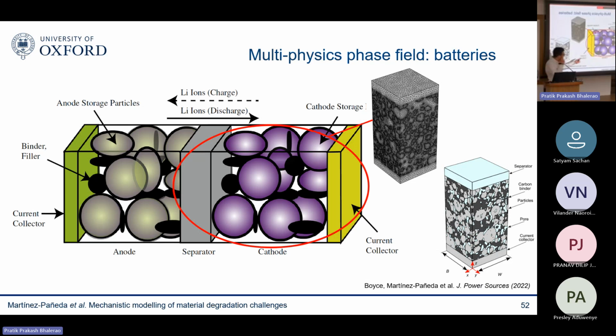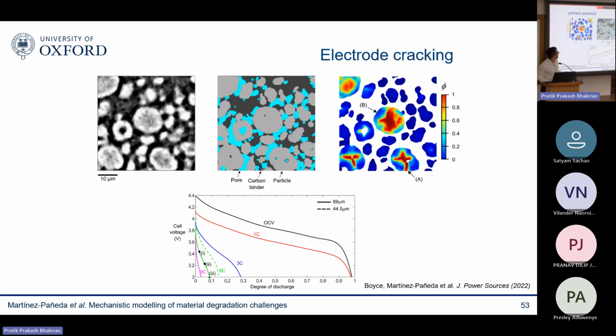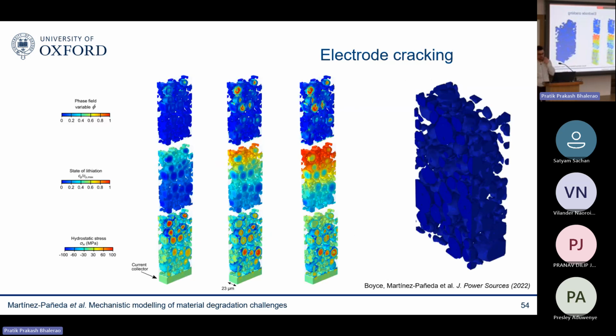But we also look beyond a single electrode particle like other groups have done, and we have taken this to the next level, to the electrode level. This is together with the group of Paul Shearing. They're very good at XCT scanning, so they can do full XCT scans. We can segment those XCT scans so we can determine not only particles, but also secondary phases, pores, carbon binders, separators. We can segment those XCT images, and then we can run our phase field simulations. And just to show you some representative results, what we see here, this should be plain, I think.